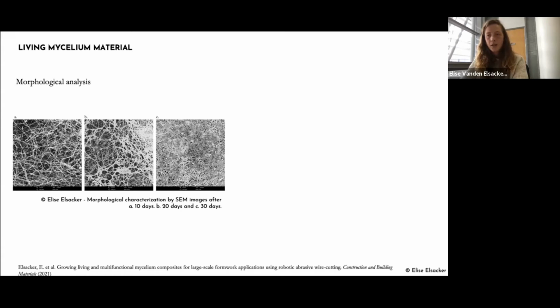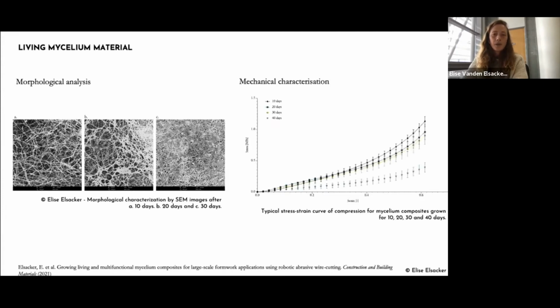But the other challenge is that when mycelium composite continues to grow, the mechanical properties will decrease over time because the organism continues to degrade the natural fibers. And this was also tested mechanically. So after 10 days, 20 and 30 and 40 days, you can see that the compression strength actually diminished.